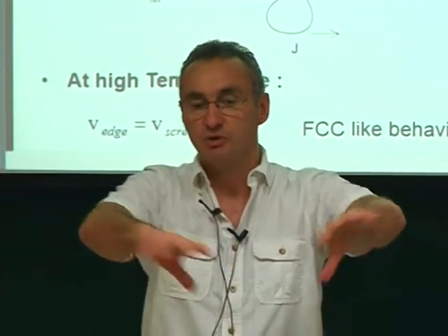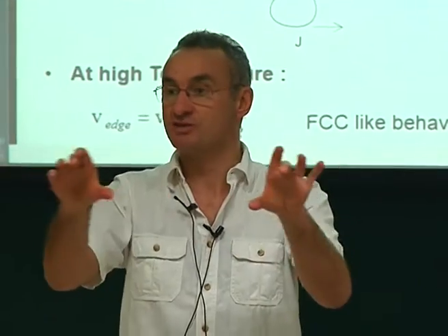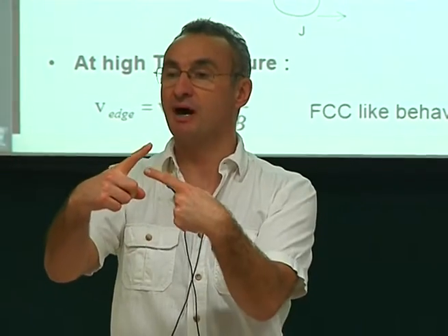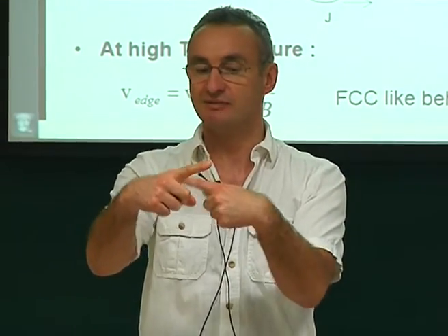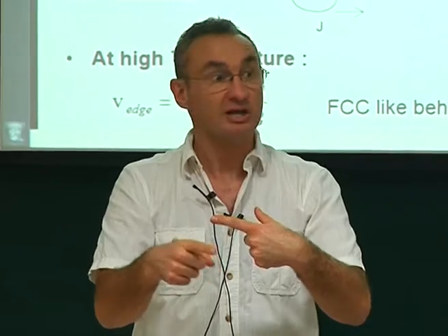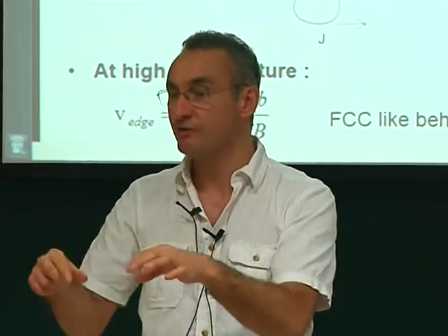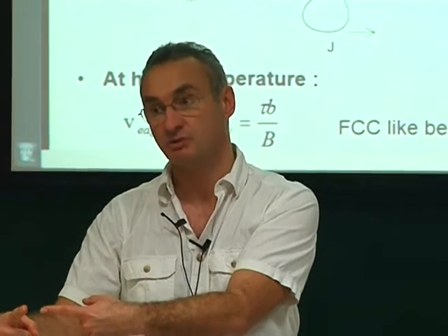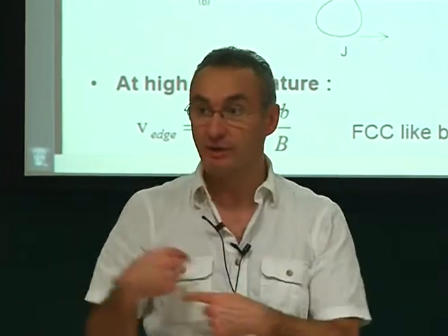Every time your dislocation loop is emitted, there will be 2 partials everywhere. And the partials are not parallel. You see, they have 2 Burgers vectors for the 2 lines. So there is no place where you have a pure screw dislocation. You can have a pure partial screw, but nearby you will have a mixed 60 degrees partial. So you never have a screw anywhere.